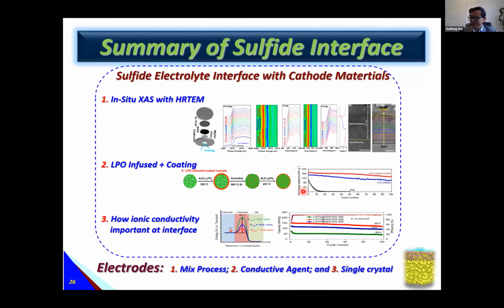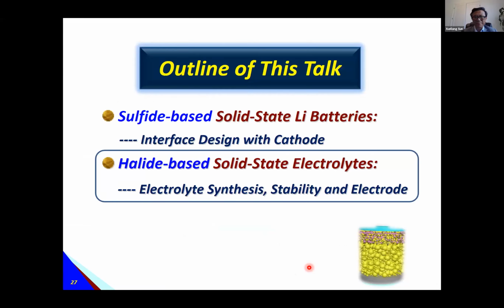So let's have a summary here. I gave 3 examples: the in-situ XAS study, the coating plus annealing, and the ionic conductivity at the interface. Using the last few minutes, about 10, I gave you a second example, halide-based electrolyte.